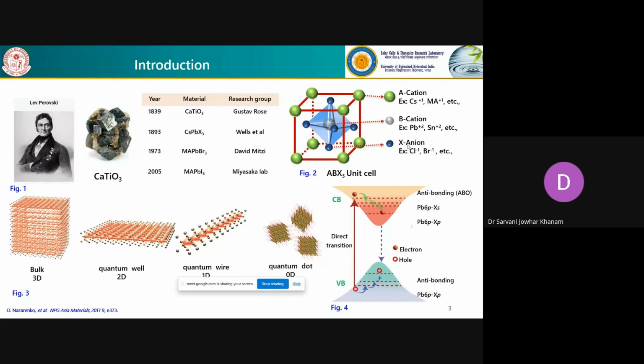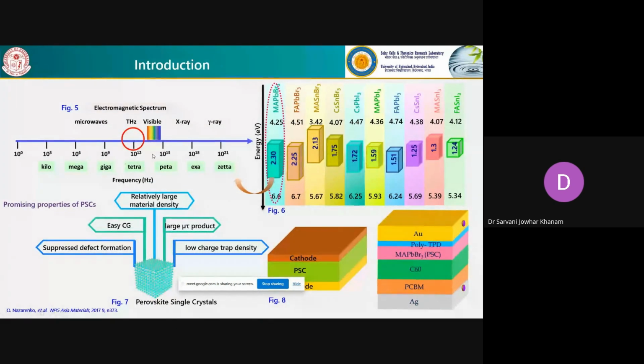As we all know, these perovskite materials are semiconducting, so the main important feature lies in the band gap. Here, the band gap of this material is formed by the combination of the lead 6p orbitals and the halide p orbitals. So depending on the necessity and the application, we can tune the band gap of this material by changing the configuration. As we can see here, by directly changing the lead composition and the halide composition, we can tune the band gap across the range of the electromagnetic spectrum. The larger band gap is suitable for higher energy radiation detection, and as discussed earlier, we can use this for photovoltaic applications as well.